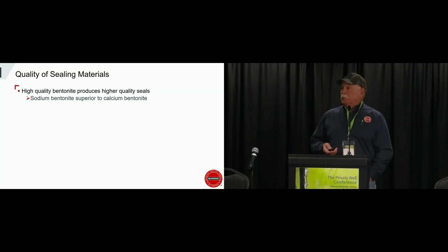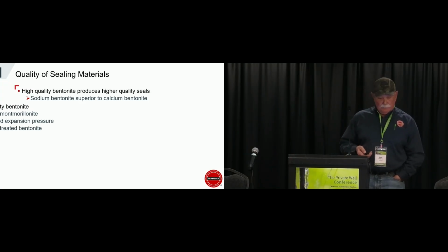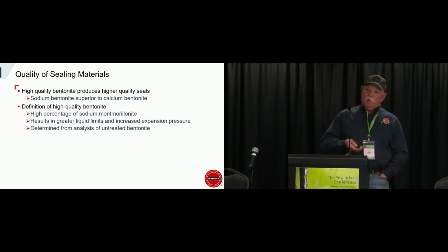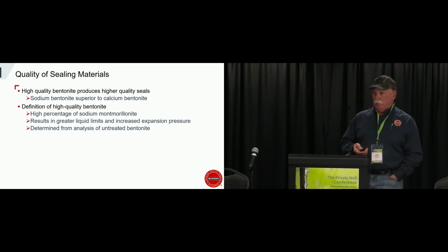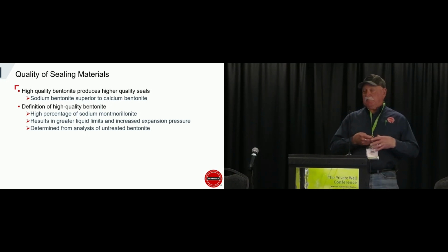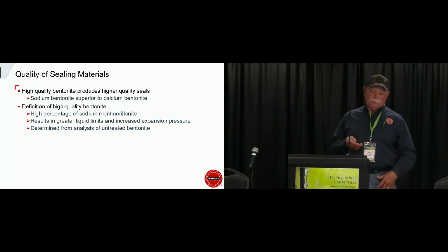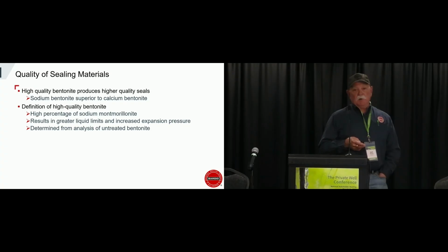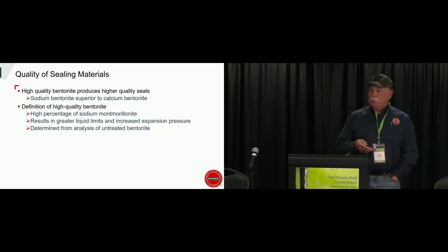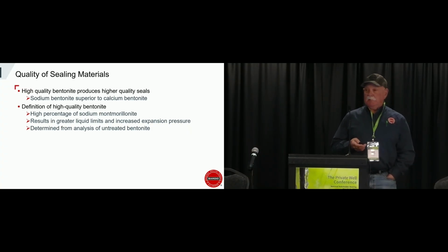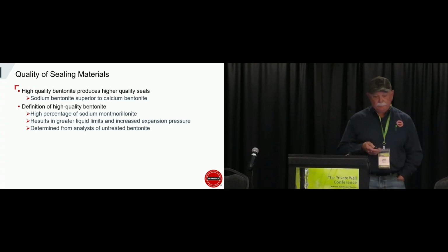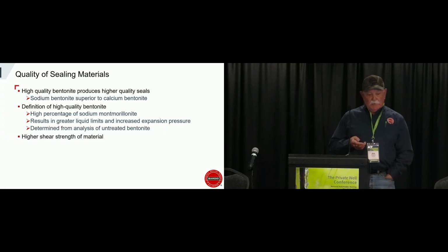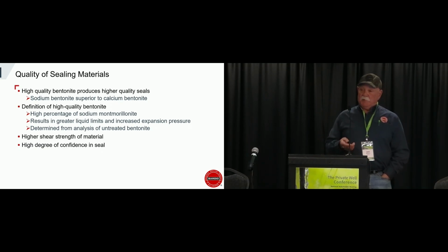Sodium bentonite is superior to calcium bentonite. So the definition of high quality bentonite: it's a high percentage of sodium montmorillonite. Montmorillonite is basically a smectitic clay that actually expands, so it results in higher liquid limits. It can take on more water to expand the structure, providing a higher expansion pressure. That's basically determined by analysis of untreated bentonite, XRD or XRF. So it has a high shear strength and a high degree of confidence in the seal.